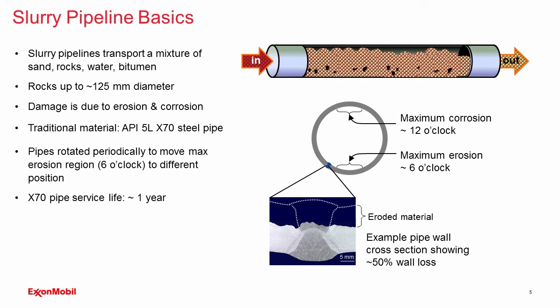The pipes, I should mention, are periodically rotated to move that heavily eroded region away from the 6 o'clock position. So every few months, the pipelines are unflanged, and that's the reason for the flanged connections that I mentioned previously. They're unflanged, rotated maybe a third of a turn or a quarter of a turn, bolted back together, and operation continues. But even with that, the X70 pipe service life is only about 1 year, and then the pipelines have to be replaced.